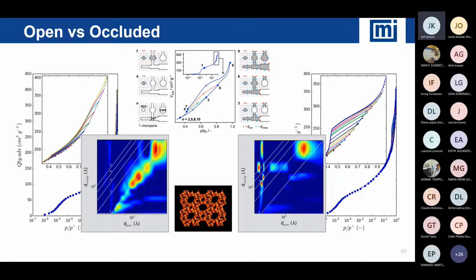So they really look like cylindrical pores. And that's the message from what's happening on the left side. Via a different treatment, notice the porosity in the window is very small, but the pores are quite large. That's a good indicator that we've got sort of an ink bottle shape, that I've got a very small opening leading to a very large pore.